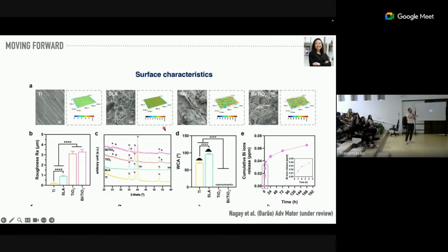The roughness of the treated surface, we use a plasma electrolytic oxidation technique. So the roughness is around 3 for the plasma electrolytic oxidation surface. We were able to deposit anatase and rutile structure in the TiO2 and bismuth TiO2. The water contact angle was very low for the treated surface here, super hydrophilic. We also have the experiment showing the release of the bismuth. Of course, we have a burst release in the beginning, but this release was sustained a little bit.